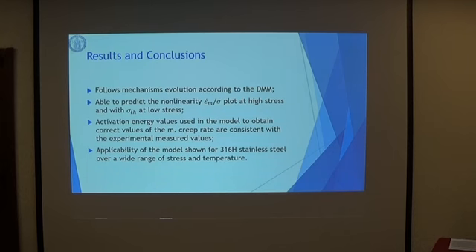So, concluding, the proposed model follows the mechanism's evolution according to the deformation mechanism maps. Then the model is able to predict the nonlinearity of the double log plots of minimum creep rate and stress, both for high stresses with the threshold stress value and also at low stresses. Then the activation energy used in the model to obtain the correct values of the minimum creep rate are consistent with the experimentally measured values. And then we demonstrated the applicability of the model with the 316H stainless steel data. I finished.